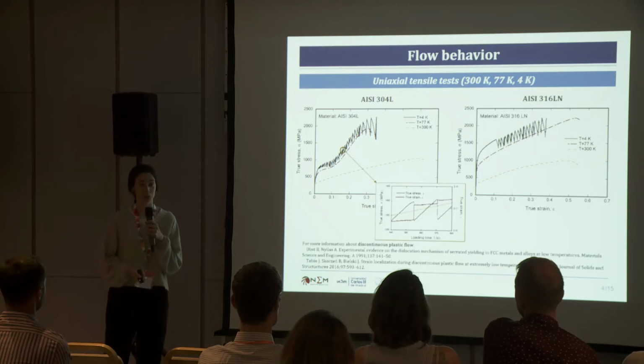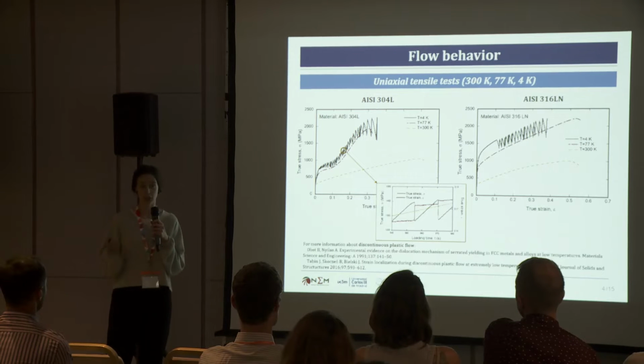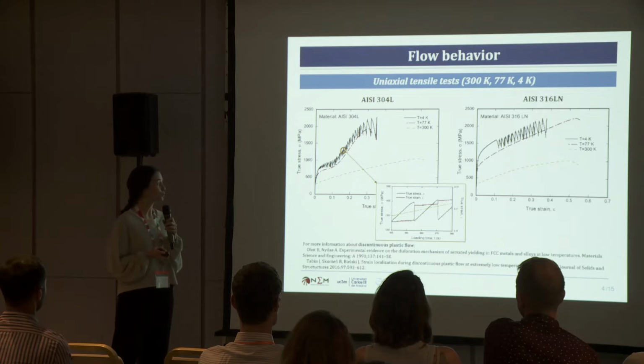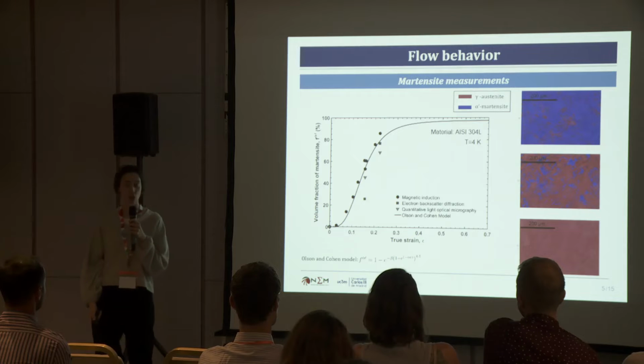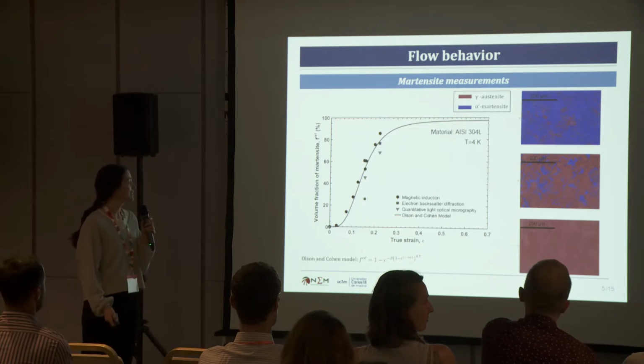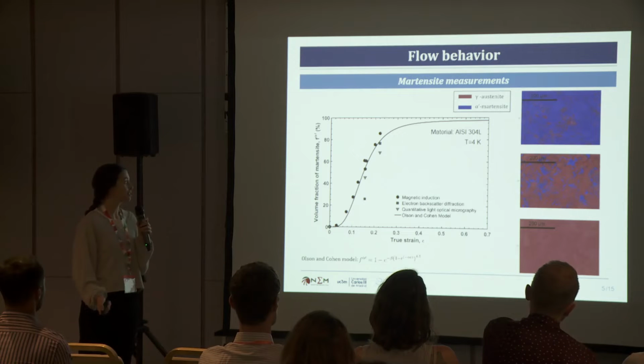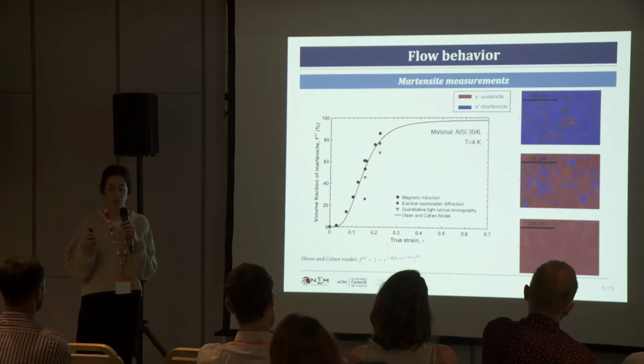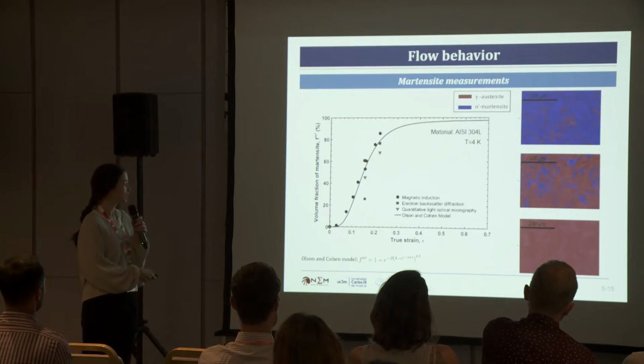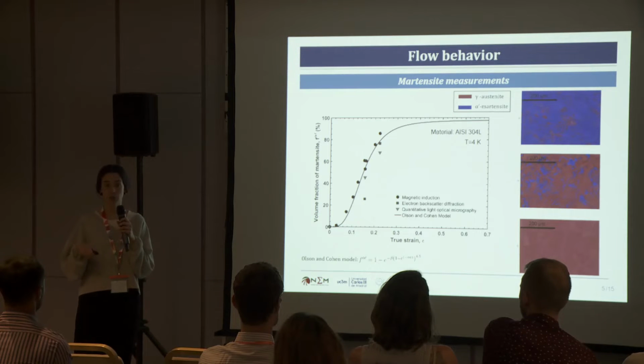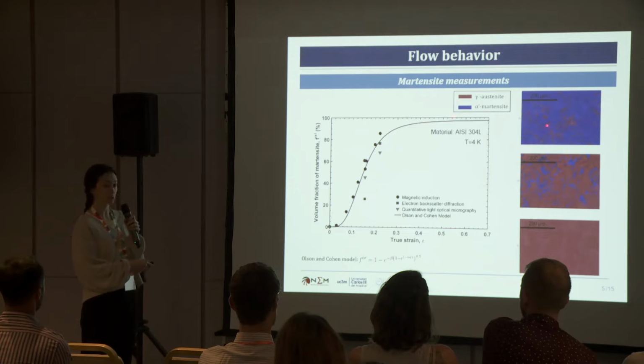I'm very sorry, but I'm not going to explain that in this presentation, but if you are interested, we can talk later, or you can send me an email or whatever. I'm going to focus on another very interesting phenomenon for this austenitic stainless steel at cryogenic temperature, the strain-induced martensitic transformation. Those two grades suffer this transformation from the austenitic phase to the martensitic phase. As you can see here, when you deform the material, the content of martensite increases. And this we can see also in the microstructure. We have performed EBSD mapping, and you can see that in the beginning everything is red. Red is the austenite, and then when you start increasing the strain, you start having blue, martensite.